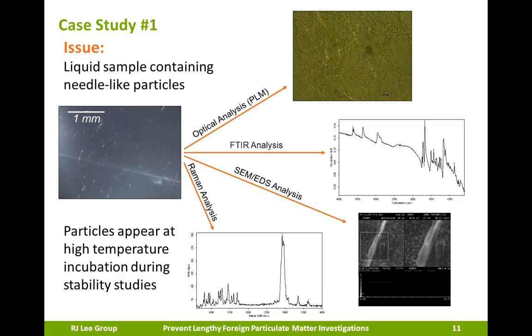Utilizing the energy dispersive spectrum that you see in the bottom portion of the image, there were elements of carbon and oxygen present. So we knew in this case study we were dealing with something that was organic. In this case, the FTIR spectrum was unusually complex, so in addition we chose to also analyze by Raman spectroscopy, and you can see the Raman spectrum that's displayed here.